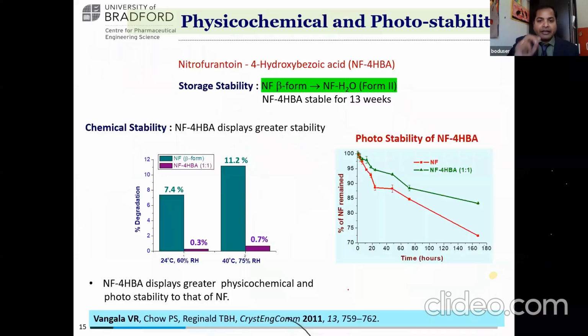For my nitrofurantoin co-crystallization, initially we prepared the first co-crystal of nitrofurantoin with 4-hydroxybenzoic acid. The problem nitrofurantoin has is that during storage it becomes a monohydrate, nitrofurantoin monohydrate. This is going to cause changes leading to poor tabletability or poor physical properties. So this is the physical stability issue that we tried to explore.